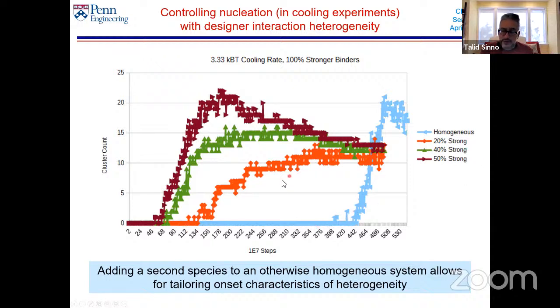So if I include now, instead of having all the particles have the same interaction strength, some buffer particles, I'm going to add some subset of particles that are stronger binders. What happens is that I drive this process to happen at an earlier point in time, because now these can aggregate at higher temperature. So this is this line. But if I put just the right amount, I can control how quickly this clustering can take place. And so this orange line, you can see it never reaches this height, and it never really starts coming down like these ones do, because I'm not getting coalescence. So by sprinkling in a few stronger binding particles, I can drive this process more gently. I'm distributing nucleation over longer times, and again, I'm inhibiting gelation.